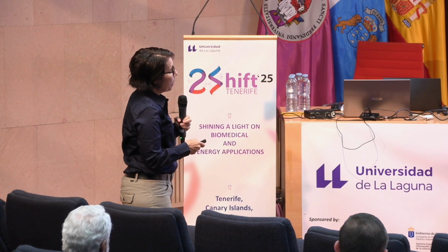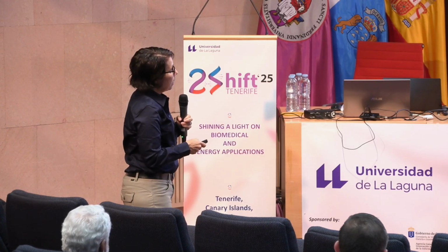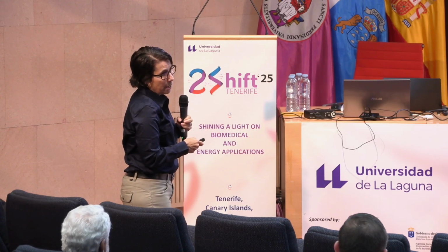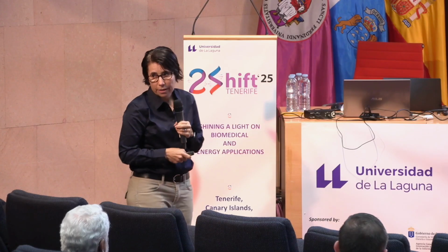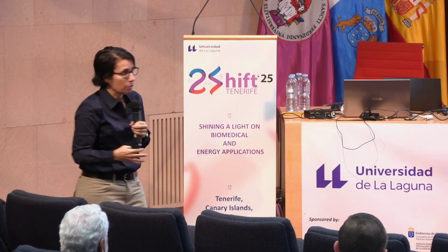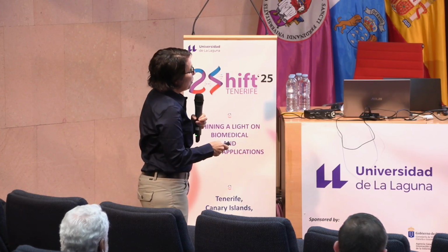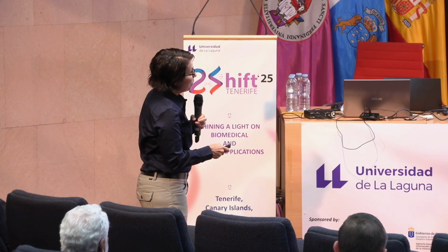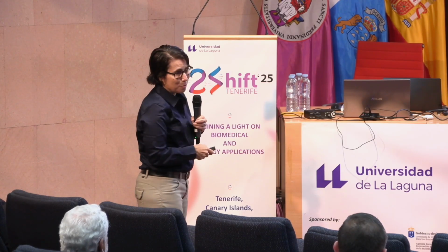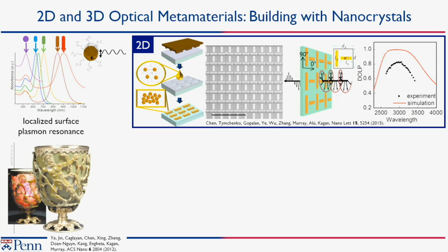So what we did was prepare circularly polarized light, look at the transmitted light, and analyze how linearly polarized the transmitted light was, to characterize it as a quarter wave plate. In calculation, you get the red curve, and in experiment, we got the black symbols here. You can see we have imperfections in our structure, so we're not quite as perfect, but it was pretty good, and we could even play around with geometry and make very broadband quarter wave plates.